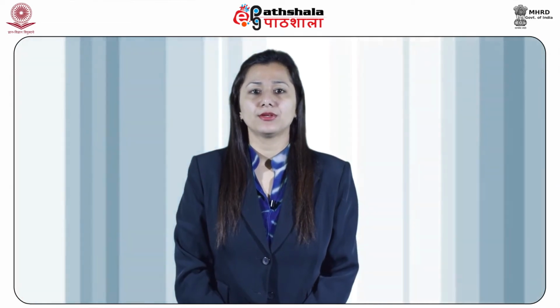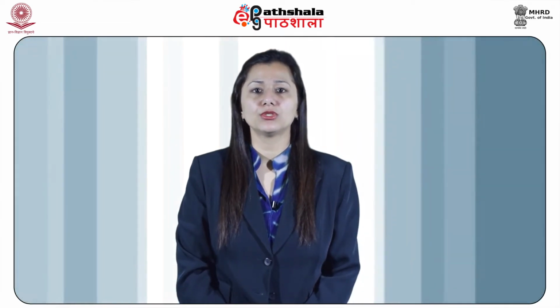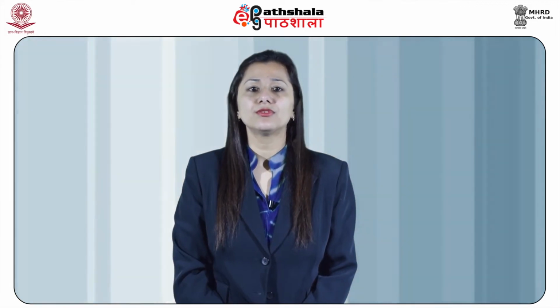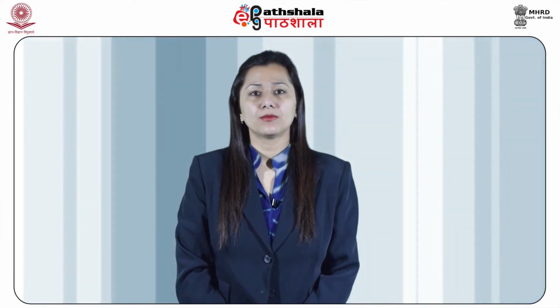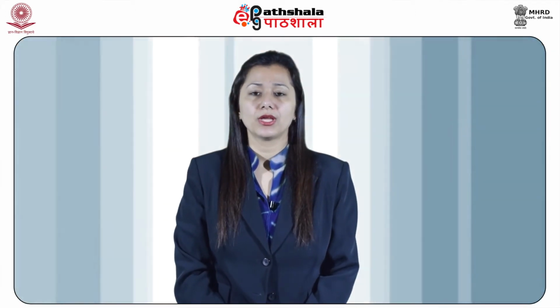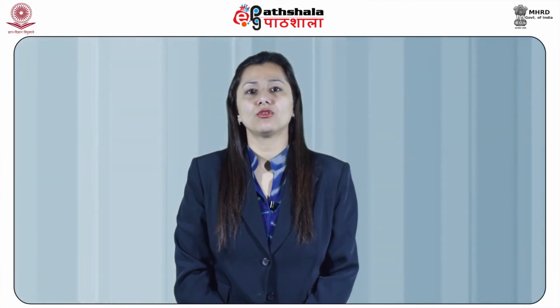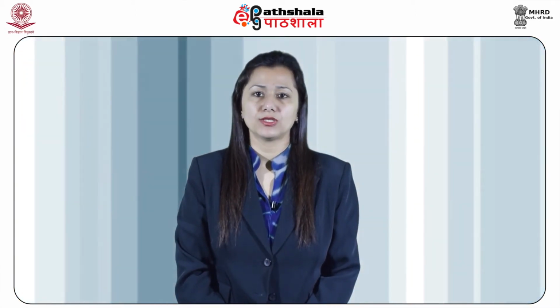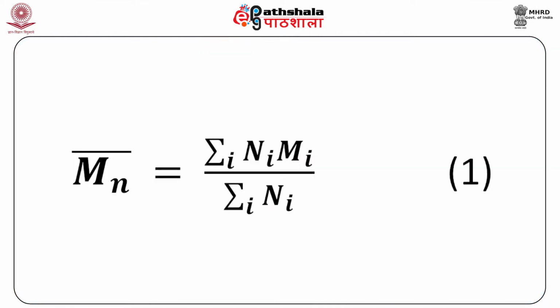Depending upon the method by which the macromolecule is produced, the same molecule may have different molar mass. Hence, for macromolecules, the concept of average molar mass is used. In order to describe the distribution of molar masses, the following averages are commonly used. Number 1 is the number average molar mass, M̄n, given by summation NiMi by summation Ni, as our equation 1, where Ni is the number of molecules each having molar mass Mi.